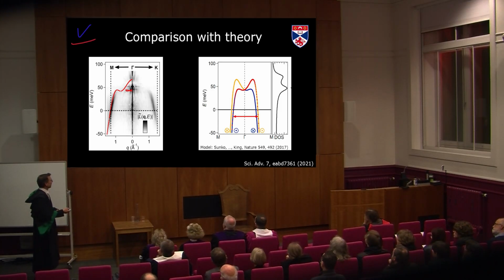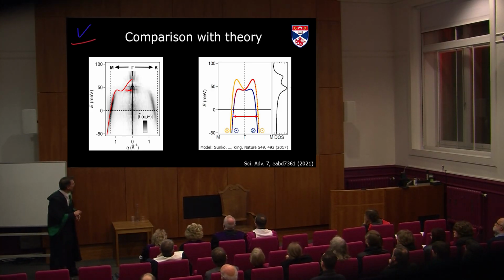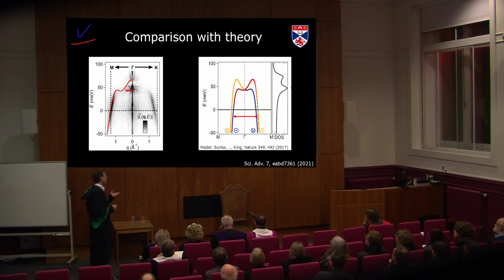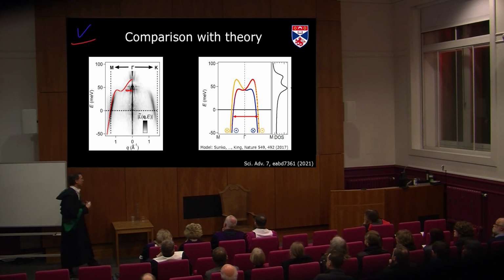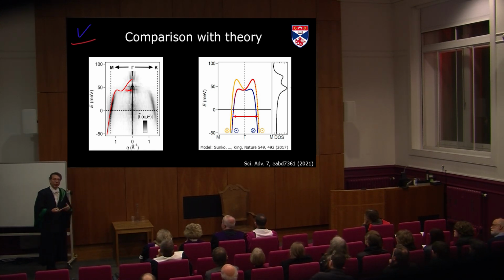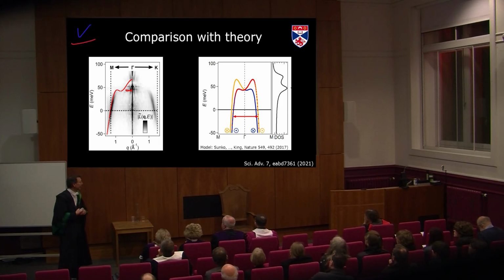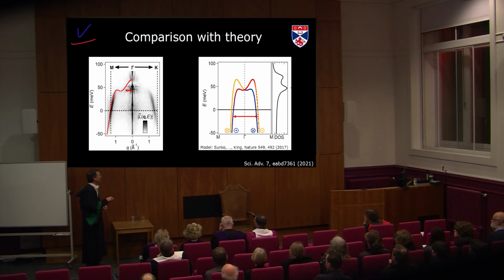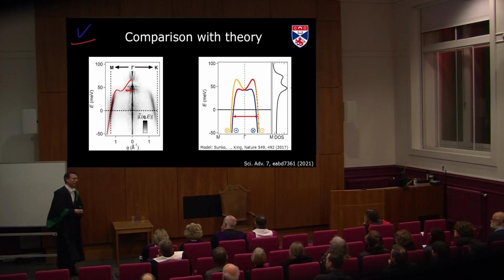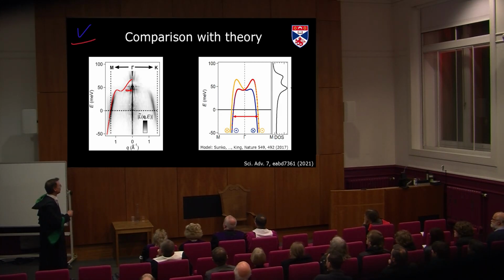And in that specific case, one can then actually see that what we get from theory is reasonably well reproduced in the experiment. And in this specific case, we can then also understand that the spin of the electrons plays a role in how the electrons behave in the material. That was one of the things we could deduce here. Although I must admit, in this specific case, my colleague Phil King could have told me that beforehand, before we looked at it. But we were able to here basically confirm that using a different method.